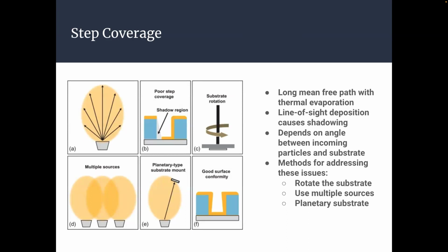Moving on to step coverage, it's pretty important to consider for PVD because all the PVD takes place in a vacuum chamber, and so the mean free path is longer because there's fewer particles around. And so for the case of thermal evaporation, it's very much a line of sight process, where if you have anything blocking the path of the particle, then it does not get deposited. So things like trenches or tall features like fins on the surface may obstruct the view of the incoming particles. There are different ways to account for this, but we can see in this figure that example part B shows the step coverage. It's not getting deposited on the left sidewall because of the angle that the particles are coming from.